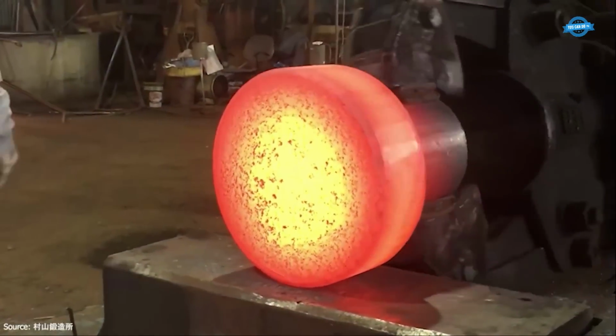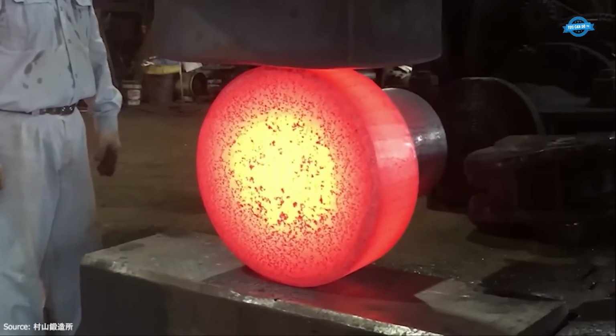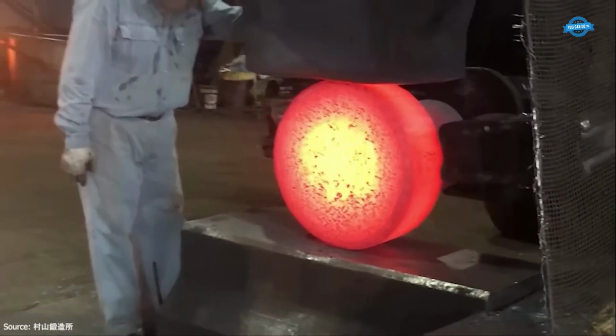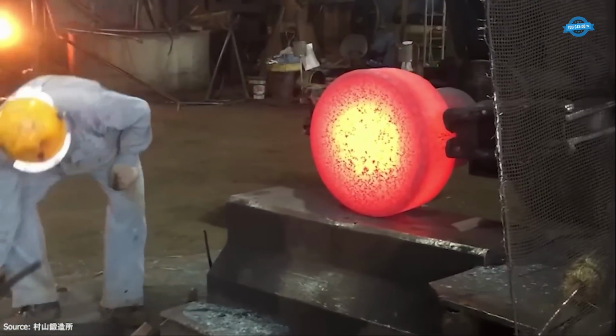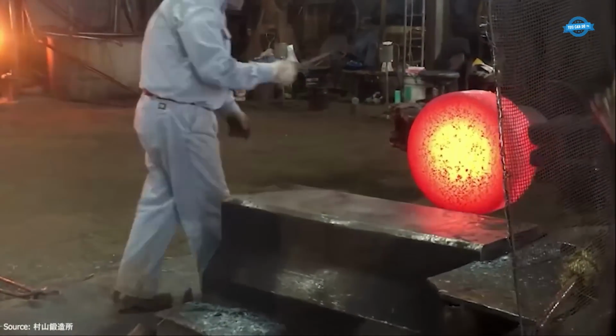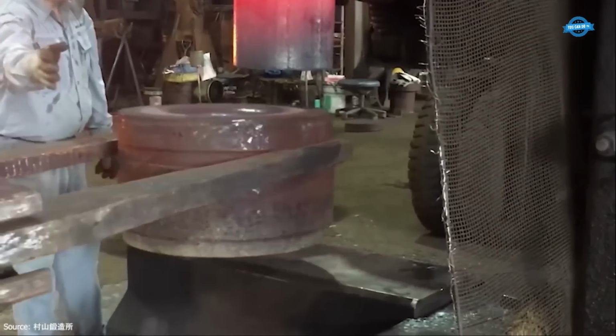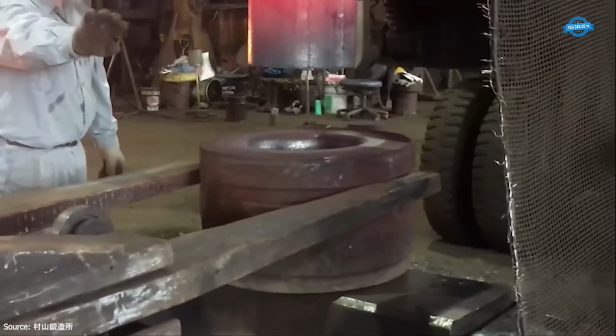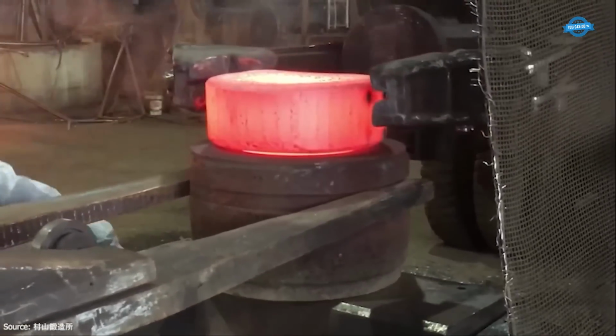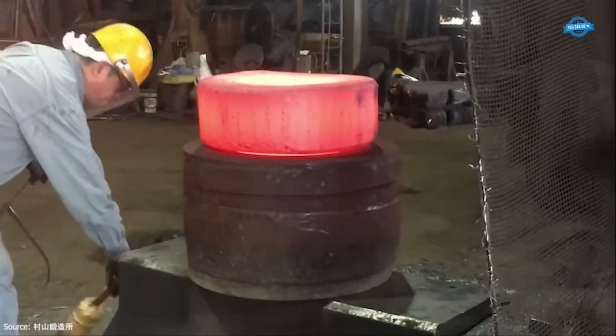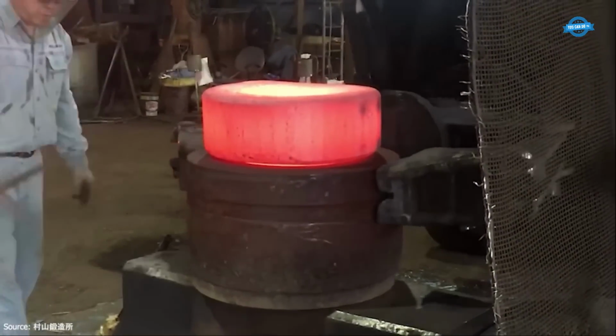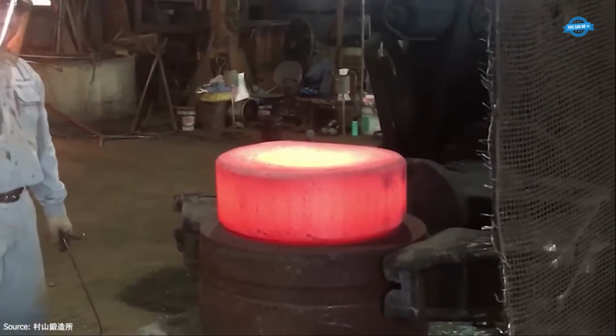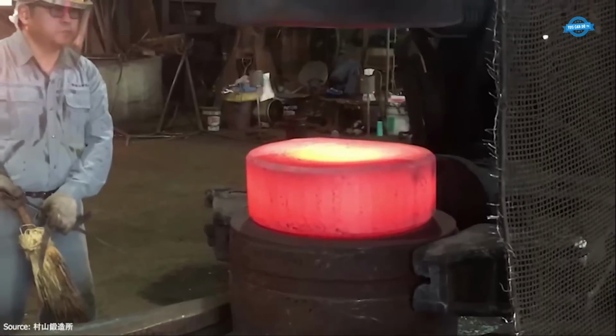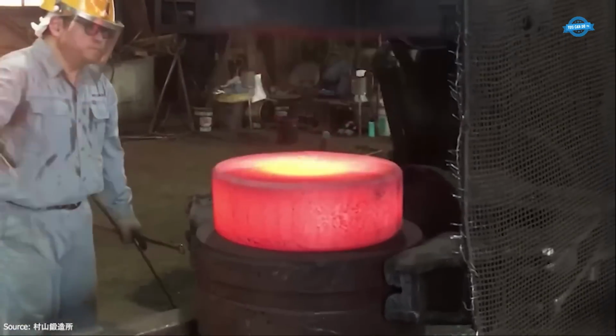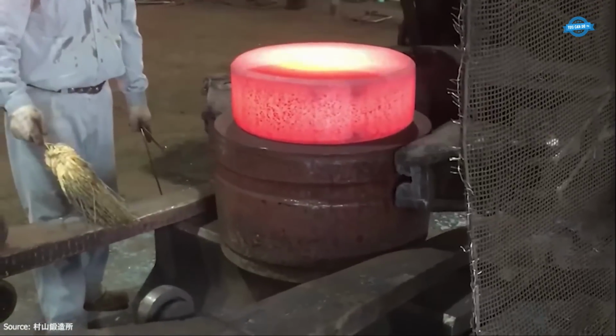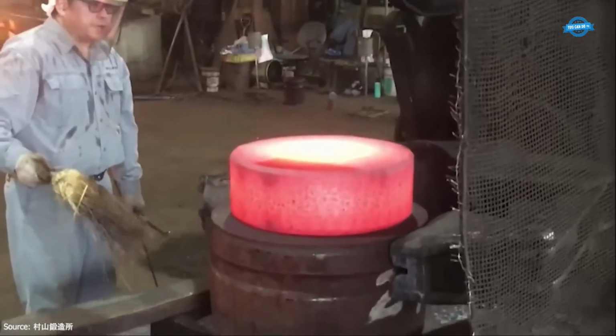Once cooled to handling temperatures, the forging undergoes initial inspections. Surface quality is checked visually, ensuring no cracks, laps, or scale remnants are present. Dimensional checks are repeated with precise instruments. Subsequent processes may include heat treatment. To achieve the required hardness and toughness, the coupling may undergo normalization or quenching and tempering. S45C typically reaches hardness levels around 200 to 240 HB after normalization.